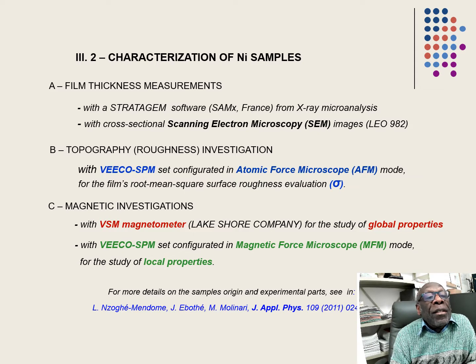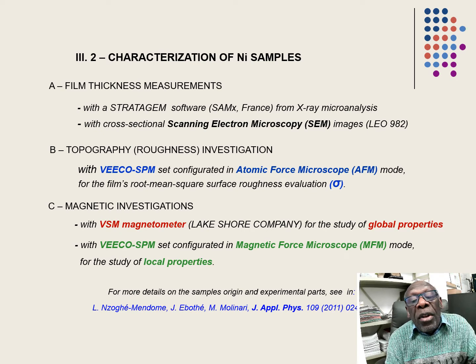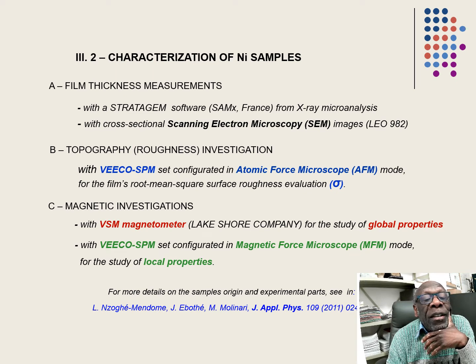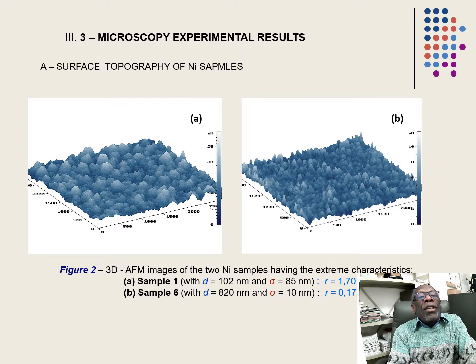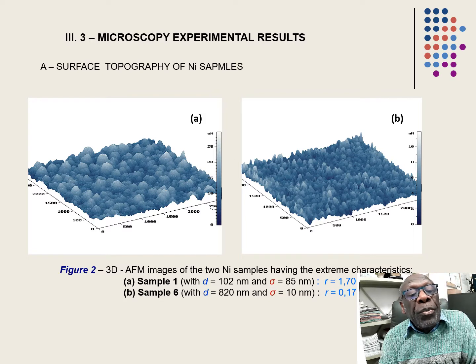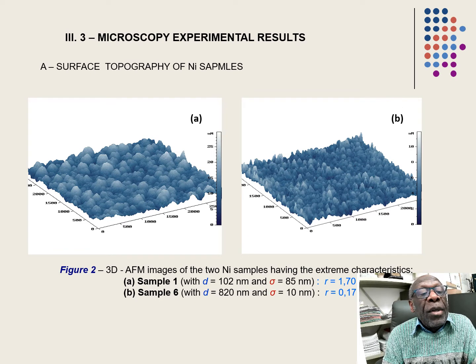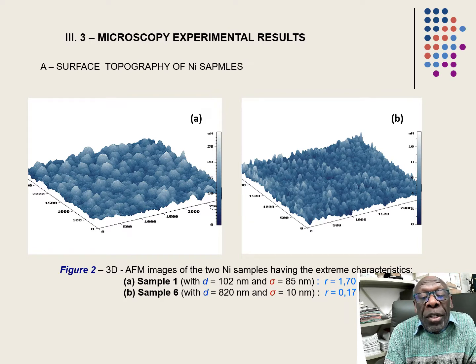The films are characterized as here: thickness by cross-section scanning electron microscope images, and the topography, that means the roughness measurement, by AFM, and global property by VSM magnetometer, and local magnetic property by magnetic force microscope, MFM. Here is the result of the topography obtained from two samples obtained from the extreme values of the scan rate. Higher scan rate gives bigger grains, smaller scan rate, smaller grains, but the two samples have globally the same morphology.